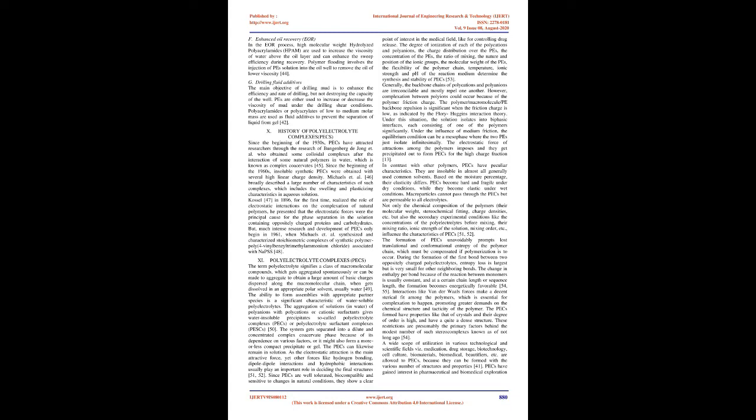Above-mentioned methods require the aqueous solution of PEs, and it should be molecular and dilute. Some PEs tend to assemble in solution, and the transition of solution from dilute to semi-dilute of some commercial PEs of very high molecular weight falls in the range of concentration generally used for the experiment, so much care is required while preparing the solution. For primary methods, the exact weight concentration of the PEs must be known. Moisture and impurities both should be taken under consideration while determining molecular weight.